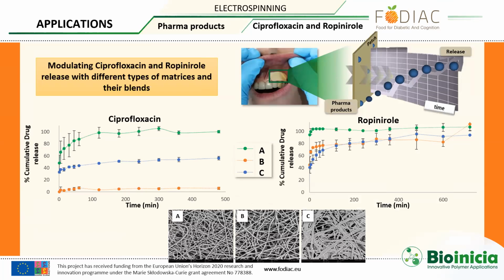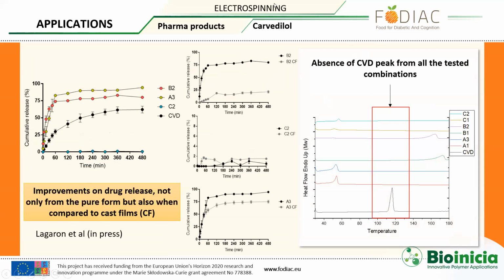We can control it. So we have been able to make ad hoc patches to deliver certain amounts of drug at the time that we prefer. Whether we want to have a patch for 1 hour or 6 hours, we can modulate this with the know-how that we now have. And in this particular case, for the carvedilol, for example, we have also observed that when we compare with the CF, which means the cast films, the drug dissolution is higher and better for our fibers, which is good for poorly water-soluble drugs, as is the case of carvedilol.